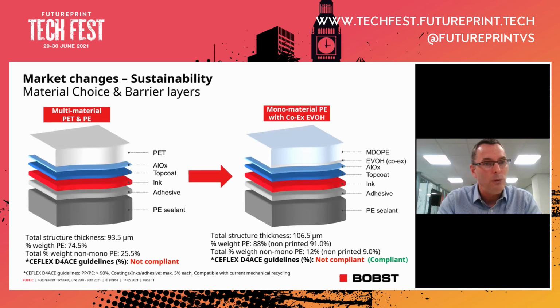If we use the percentage weight of the polyethylene in this first mixed polymer solution on the left, we can see we have a non-mono material weight percent of about 25.5%. This is obviously significantly more than the 10% CEFLEX guidelines, and hence the drive to move to more mono material structures. For the structure on the right-hand side of the slide, we have a two-layer bilaminate structure again, but this time it's made up of a 25-micron machine direction orientated polyethylene, and again, a 75-micron sealant web.